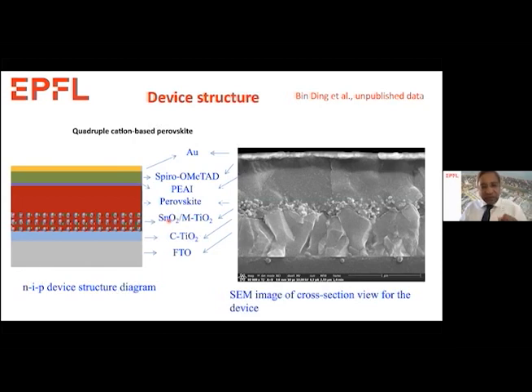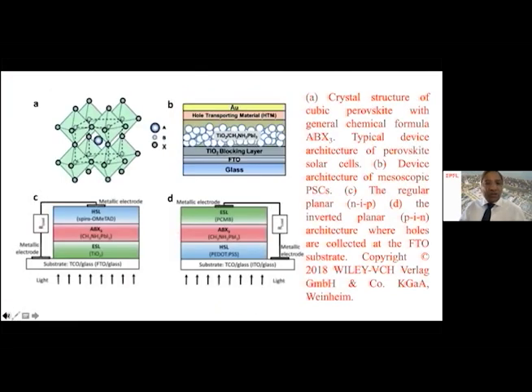So you will see this towards the end of my presentation, but just note here that we have two types of metal oxide layers as an electron transport layer, followed by a perovskite material deposited on top, which is not very visible, but imagine that we have a very thin layer of a two-dimensional perovskite. Now let me go back and highlight what is two-dimensional and what is three-dimensional. When we have ABX3, where a cation is inserted in the cavity of the perovskite lattice, it's called a three-dimensional perovskite.